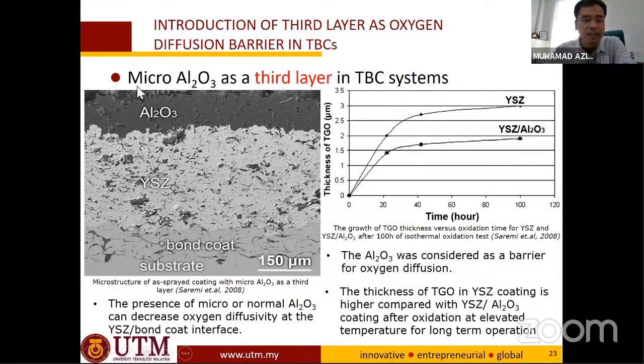The one that I showed earlier. And this is the other layer that we deposit, alumina. So alumina as a third layer can reduce the oxide formation at the TGO layer, or the spinel formation. You can see here, based on the TGO thickness, because as I say, TGO thickness is very crucial. You need to have a thin and continuous TGO. It becomes the barrier. So if you have only this one, the ceramic coating.